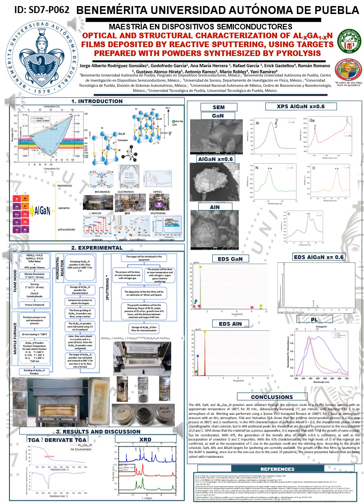The experimental process can be divided into three main parts: powder synthesis, balance the reaction equation for obtaining AlGaN by pyrolysis, which is equation 1. Using this equation, calculate the moles and grams of the reactants to be used. Inside a fume hood in a Teflon beaker, add 20 ml of toluene, add the aluminum nitrate and the gallium nitrate. On a thermomagnetic stirrer grill at 111 degrees Celsius for 15 minutes to dissolve the reagents, add the carbohydrazide to the mix and keep it for 20 minutes at 111 degrees Celsius so that the toluene evaporates until a viscous compound is obtained.